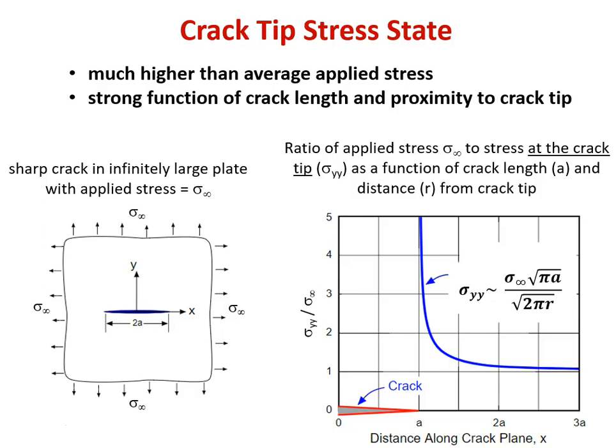So if we start over on the left-hand side, we have a schematic of a material that's an infinitely large plate again, and it's now being loaded in two directions. This is biaxial loading. So we have sigma infinity, which means basically the average bulk applied stress out on the edge of the plate. It's being loaded in both the x and the y directions, and it's got a sharp crack, meaning that we're assuming it's atomistically sharp at the tip. We're not defining a radius. We're figuring at the tip it's just literally coming up on the equilibrium interatomic spacing of two atoms in the lattice of whatever crystal you're in. And it starts out with a length of 2a.